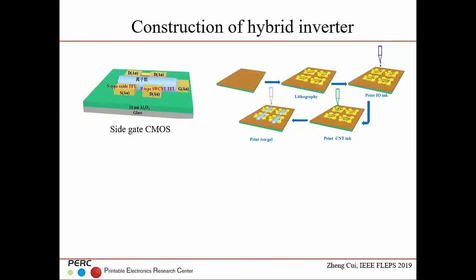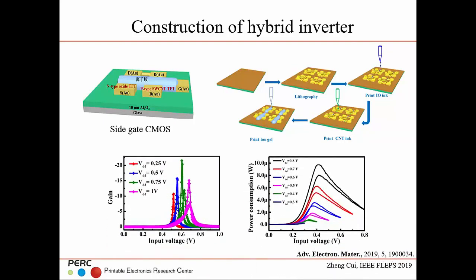And we also made a side gate CMOS, where we use the ion gel as a dielectric, using the side gate to control both transistors. So that's the printing process. All the electrodes are made by normal lithography, but the semiconductor is done by printing. Also, the ion gel is done by inkjet printing. So that's the characteristic of the inverter, where this is the gain, and this is the power consumption, about a microwatt. So it's not as good as the carbon nanotube inverter.